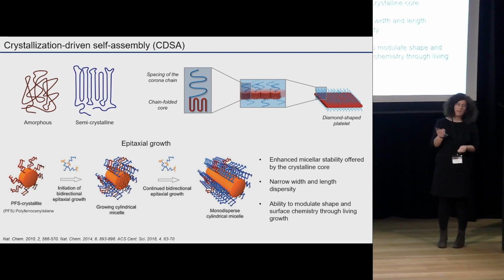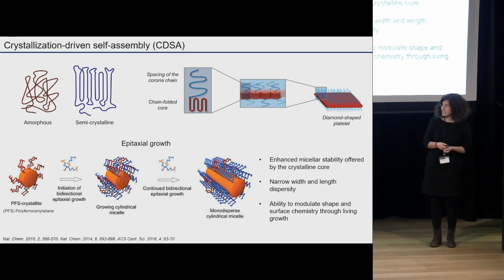So in this technique, we use semi-crystalline polymers that, as you can see here, have this very ordered and packed structure that distinguish them from amorphous polymers. And this packed structure allows them to assemble in two dimensions. Those are the platelets that I was talking about just earlier. This technique was pioneered by Professor Ian Manners in 2010. And what they found is that from one single crystallite, they can actually grow the nanoparticle in both dimensions. And the length of the nanoparticle can be controlled by how much polymer you add in. So if you add X amount of polymer, you're expecting the nanostructure to get to a specific size. And this is how you achieve control over the nanoparticle size.